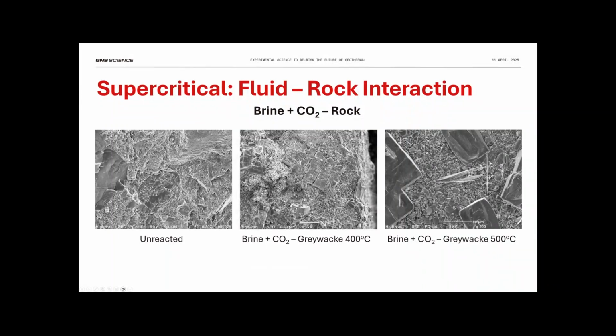There's also a lot of secondary phases. These cubes are anhydrite. You can see again at 500 degrees, we've got very nice anhydrite crystals growing and a background of albite. And these needles are again, I think, an amphibole of some kind, possibly actinolite. What's interesting is the only difference between this experiment and the previous one is the CO2. So why is there no quartz forming in this experiment?